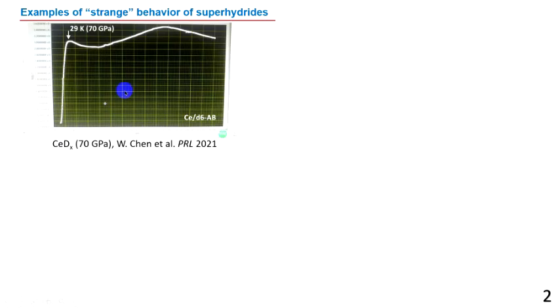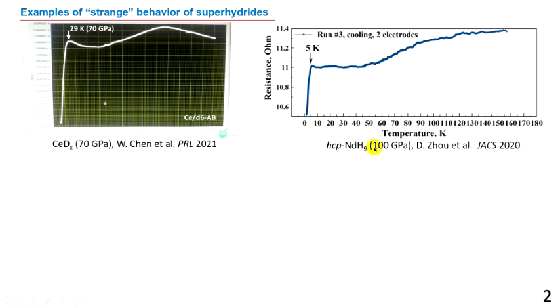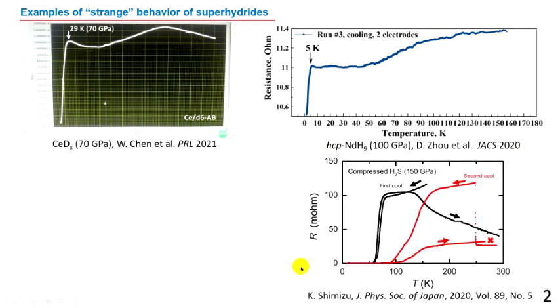Let me give you some examples of strange behavior of superhydrides in a normal state. The first picture shows the behavior of cerium tetrahydride synthesized together with Wuhao Chen in Jilin University in 2021. We see a quite big wave in the normal state resistance of this hydride, which is definitely strange. The next example is hexagonal neodymium hydride NdH9, synthesized and investigated in 2020. We see that the normal state behavior of this hydride strongly deviates from the Bloch-Grüneisen fit, which can be used for normal metals.